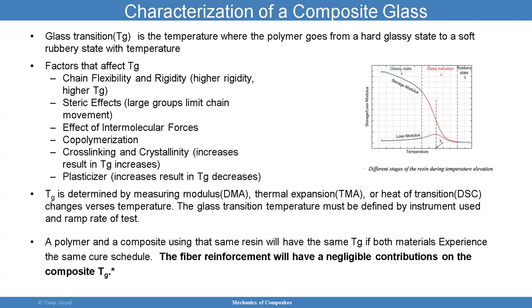The TG again is determined by measuring modulus using a dynamic mechanical analyzer. You can also do it with a thermal expansion test, TMA, or like I said before, the DSC, and it can help identify that. The glass transition temperature must be defined by the instrument used and the ramp rate of the test. Here you can see that's a storage modulus, that's a loss modulus, and things are changing over here. So we can see we have the glass transition occurring somewhere in this red portion. I went from glassy state to rubbery state, and right in the middle, we can call it a TG as one approach. Here, I'm calling it over here because I can see a change in loss modulus. It went up and it dropped with temperature. So something's going on there, call that TG.